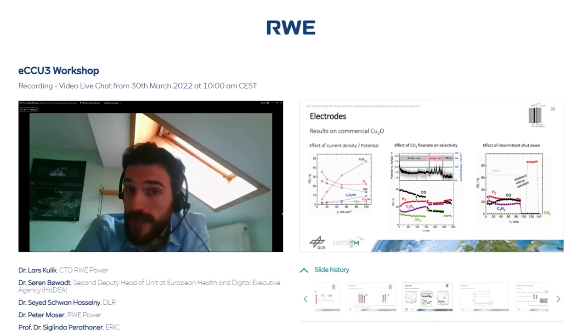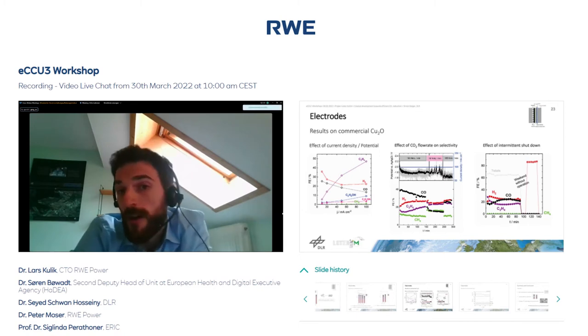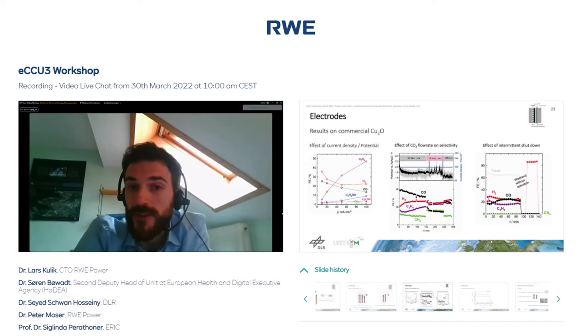And in the middle, you can see a change, for instance, of the CO2 flow rate, at a rather high flow rate in the beginning of 180, changing to 18 normal milliliter per minute. We see that this affects the CO production, for instance. So CO goes down while methane goes up, which can be explained in that CO is the first step of the reaction. And if you have a quite high CO2 mass flow, this would lead to CO leaving the surface fast and no chance for CO to further react.